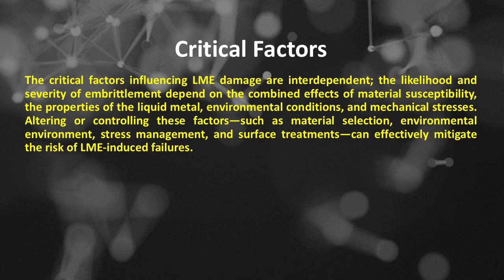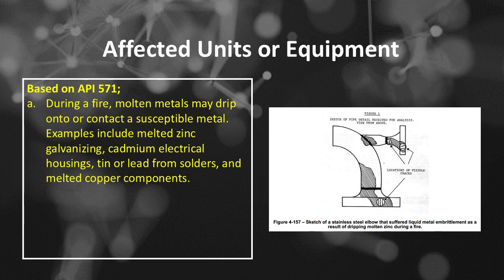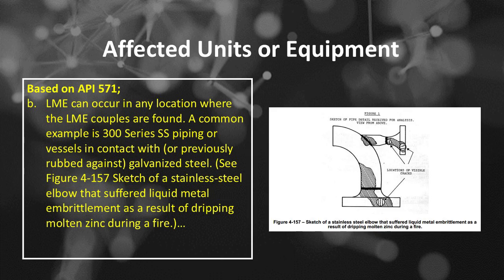of LME-induced failures. Liquid metal embrittlement damage affected units or equipment based on API 571, number A, during a fire, molten metals may drip onto or contact a susceptible metal. Examples include melted zinc galvanizing, cadmium electrical housings, tin or lead from solders, and melted copper components. Number B, LME can occur in any location where the LME couples are found. A common example is 300 series SS piping or vessels in contact with, or previously rubbed against, galvanized steel.